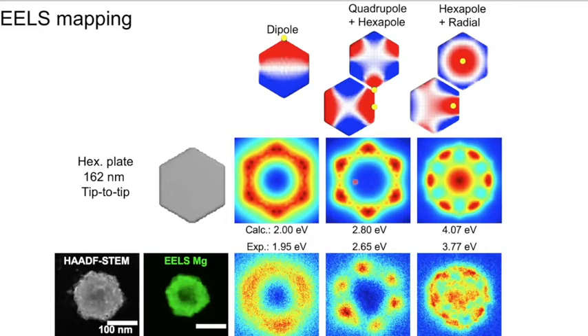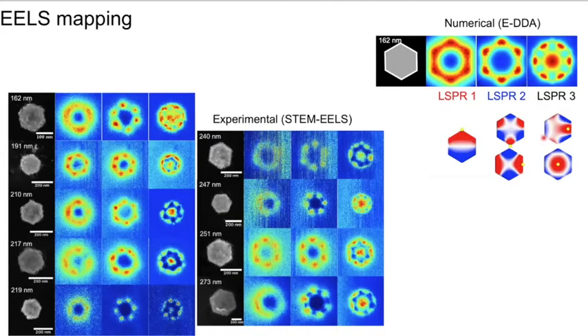The second mode we see, though, is different. And it's not a single mode. It is two modes that are not exactly degenerate, but they have very similar energy, so they're excited at the same time. And this is basically the combination of a quadrupole here and a tip hexapole. Our next mode is in fact an edge hexapole, which is not degenerate with the tip hexapole, and a radial breathing mode. And these are the patterns they form. So we're able to look at that on many, many particles. Here's nine of these particles. They always have the same modes.